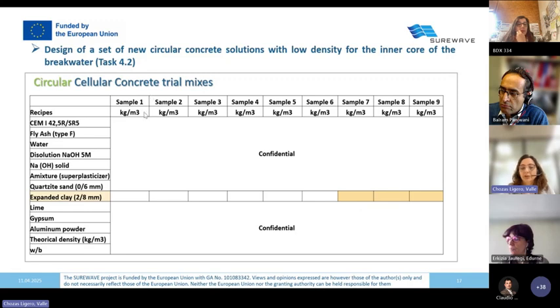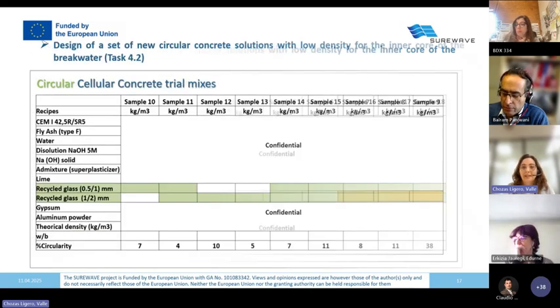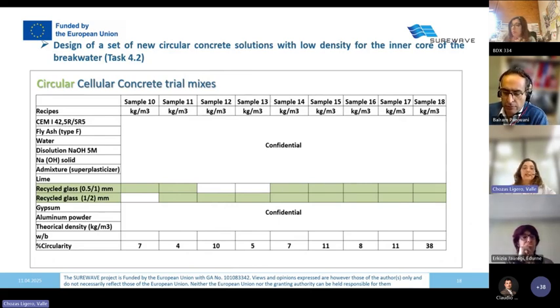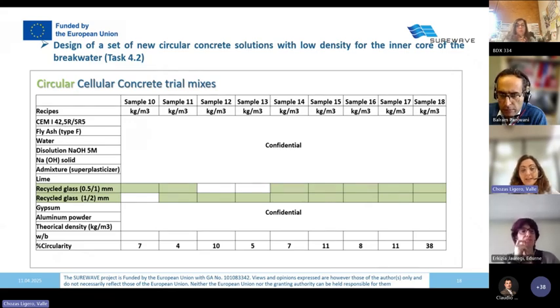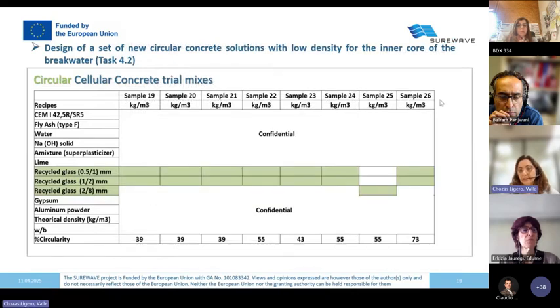From sample 1 to sample 9, the aggregates used were natural aggregates and expanded clay, but the density results were poor. In the next doses, recycled glass aggregates were used. They are lightweight aggregates, and the density results improved, and circularity also, until dose 26, which was made with recycled glass aggregates of different types, proportions and sizes. And the final circularity was 73.